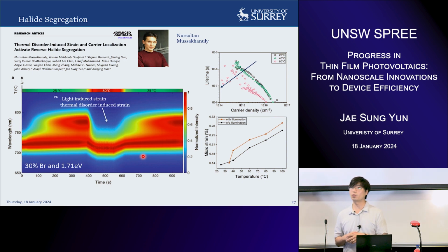I'm going to keep talking about wide bandgap perovskites, and one of our students, Nur Sultan, has done very interesting studies on wide bandgap perovskites. As you know, when solar cells operate, they will have a higher temperature than 25 degrees. So what will happen under higher temperature, say 80 degrees, for wide bandgap perovskites? There happen to be some reports on the suppression of the phase segregation at high temperature, and Nur Sultan has done some PL measurements.